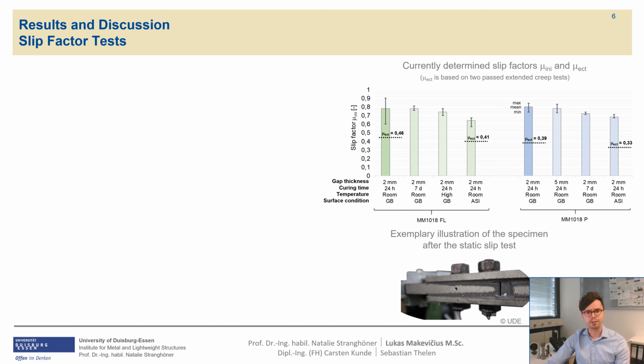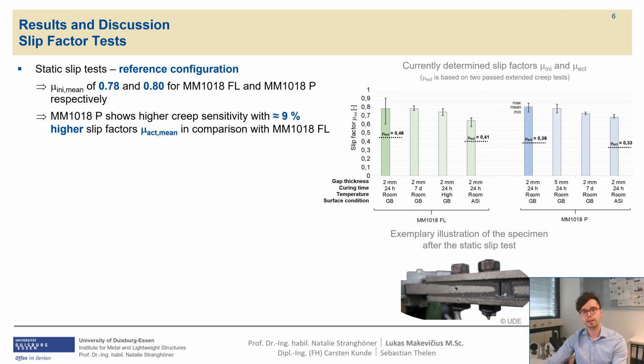The results of the slip factor test are graphically summarized in the chart on the right. The static slip test carried out on the reference configuration showed that the slip factors mu-ini mean, considering the initial preload when the test started, are comparable with 0.78 and 0.8 for the liquid and pasty material respectively. It must be mentioned though that consideration of the actual preload at slip, in form of a slip factor mu actual mean, shows higher creep sensitivity for the pasty material in comparison with the liquid type of MM1018.